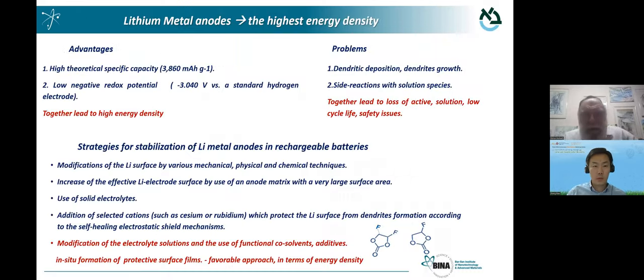So when we think about the advantages and problems of lithium metal anodes, it's clear the advantage is high energy density, which is obvious. The problems are dendrites, reactivity. Stabilization of lithium metal anodes in rechargeable batteries is a big challenge, an important challenge. And there are many options. People describe modification of the lithium surface, increase of the effective lithium electrode surface, use of solid electrolytes, addition of selected cations like cesium and rubidium that could change the surface situation.